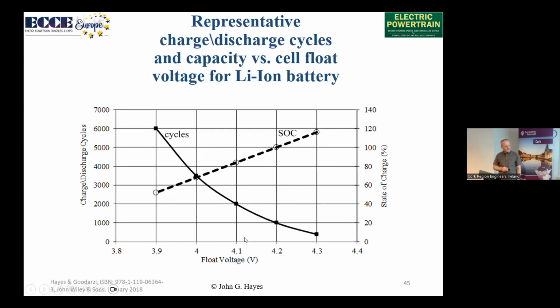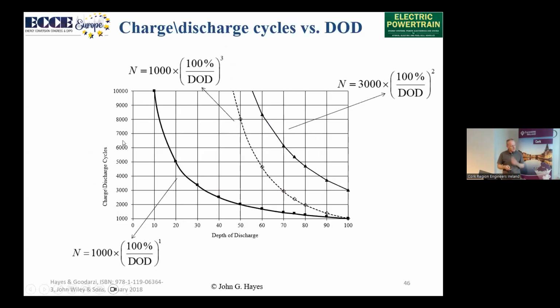So typically, we know that the lifetime, the number of cycles we can withstand, is going to increase as we push down this voltage, but the only catch is we also reduce the state of charge that can be moved within the cell. But things have moved on and are quite impressive, but this is where we certainly were once. When I first started this work, I would have good conversations in Detroit on some of these cells. And basically, over here on the y-axis, we have the number of charge-discharge cycles, fully charged and fully discharged. Let's say our baseline is 1,000 cycles, and therefore we discharge it 100%.